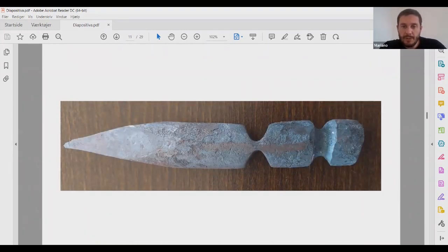Also, if you work with the guillotine, it's important to keep in mind the thickness of the blade you want to get. Here it is around 5 millimeters now. So if we want to have a 5 millimeter blade, this is not okay because we are going to get maybe 4. We need to keep some material to work later, and it's better to have, for example, 10 than a very thin material, because when we work all this part, this is going to break because we are going to maybe move the piece or start to bend it sometimes, and this is going to get the crack here.